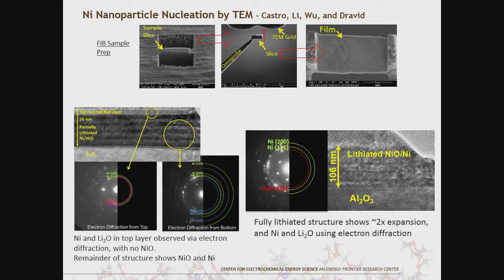For TEM work being done by Dravid, they've looked at samples partially lithiated as well as fully lithiated. What's interesting is that for the partially lithiated one, the multilayer itself is almost unperturbed except for the top layer, so in this case we had just lithiated the top layer of the multilayer. When it's fully lithiated, you can still see a multilayer there, but it's been kind of chewed up a bit.